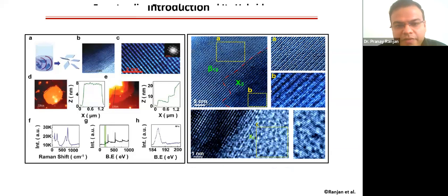However, when I was trying to investigate the properties of borophene, I ended up with two different kinds of structure, that is the beta 1,2 and the chi3. What was phenomenal here is that we found a new phase, a strain-mediated phase, that does exist between the beta 1,2 and the chi3 phase. So we tried to dig more into it in the latter part of our research, because at that time we didn't have a very good TEM.